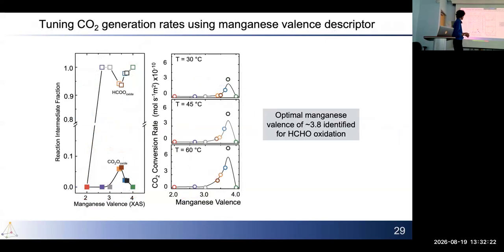When we measure the actual reaction kinetics, at 3 different temperatures, we again find a similar trend, in that at around 3.8 manganese valence we see maximum chemical reactivity. So piecing these two observations together, we could show how maximizing this carbonate reaction intermediate would lead to higher overall reactivity, and that is related to the manganese valence descriptor.